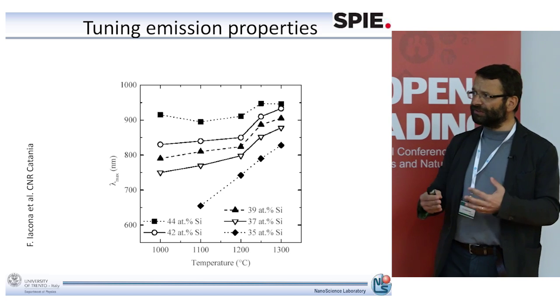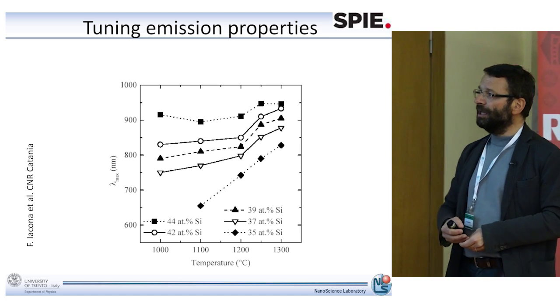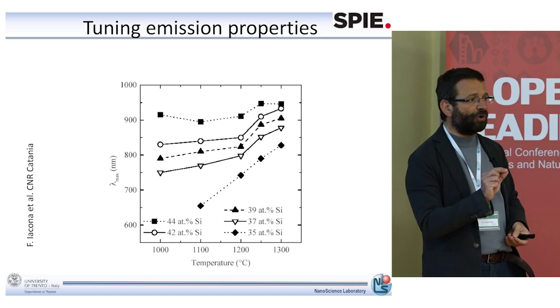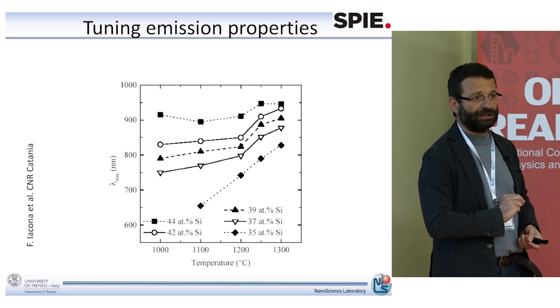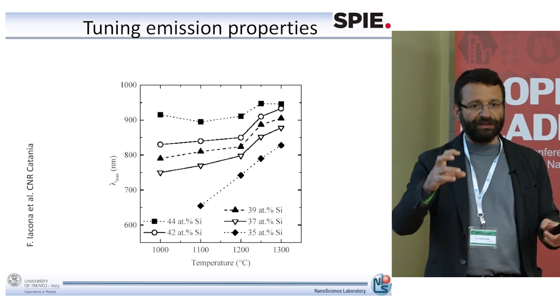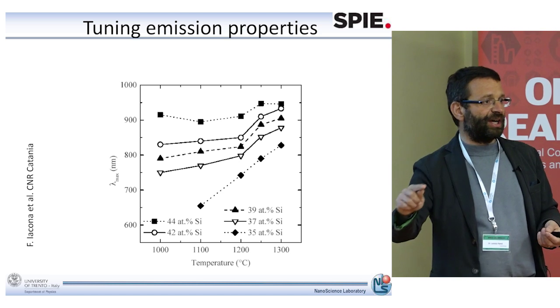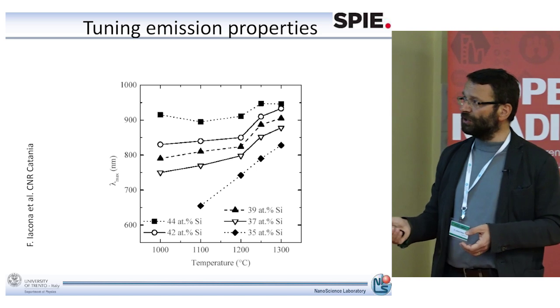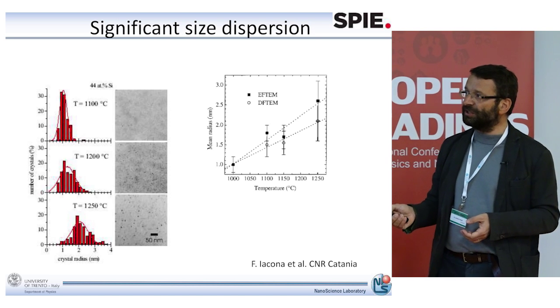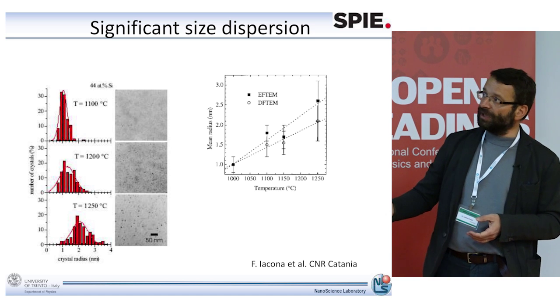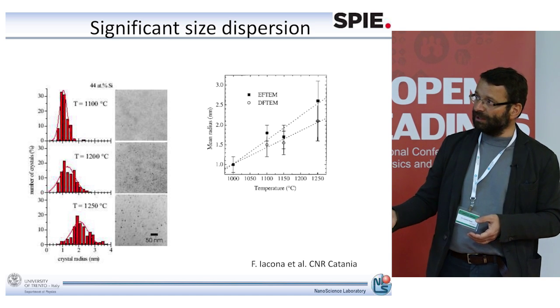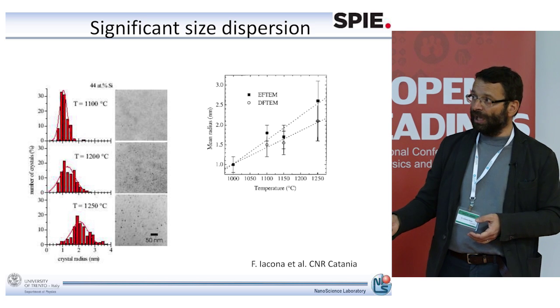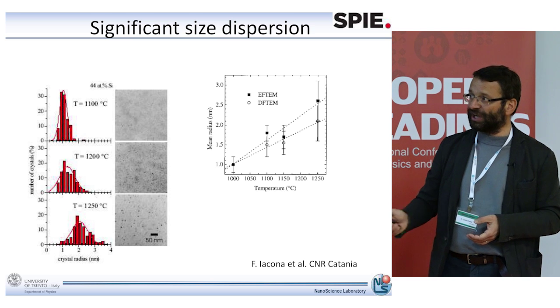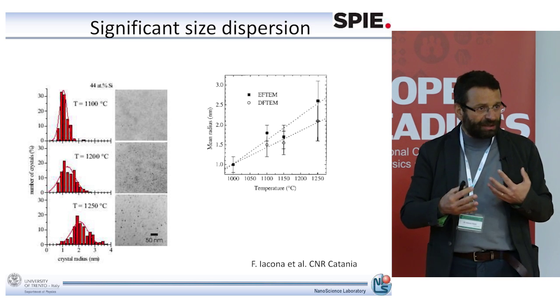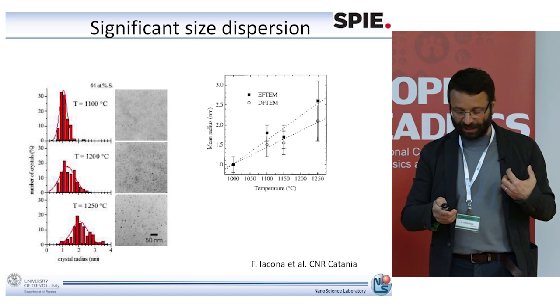One problem with this self-aggregation of the nanocrystal is associated to the fact that you do not control precisely the dimension of the nanocrystal. So what happens is that they do aggregate, they do form, but you have a huge size distribution in the nanocrystal. And so here is an example of the typical size distribution that you get in your field. So the average size is growing when you grow the annealing temperature, but even though the average size is growing, you have a quite large size dispersion. So this can be an issue for some kind of application.